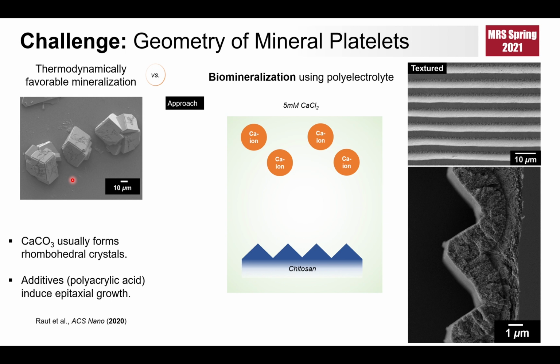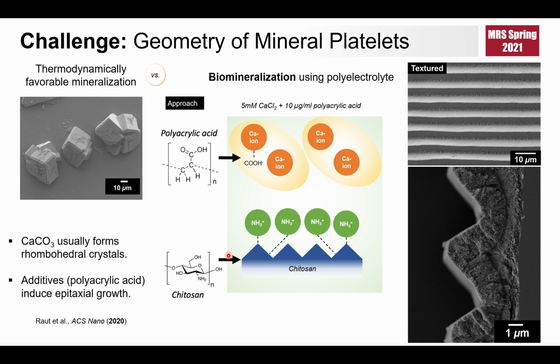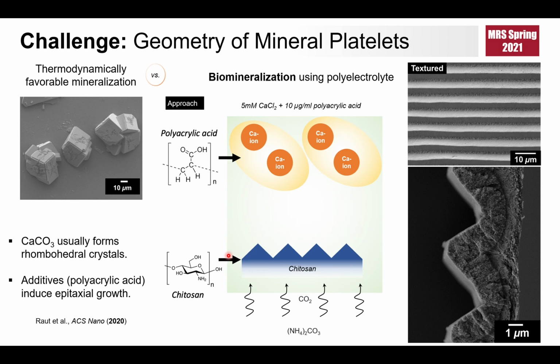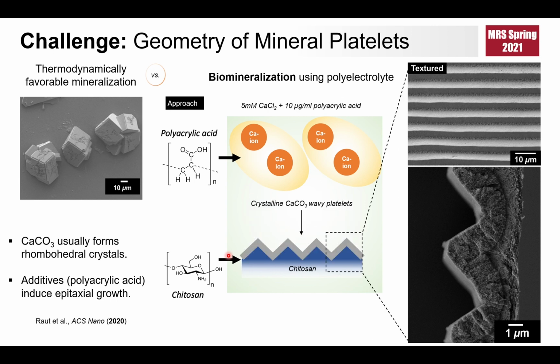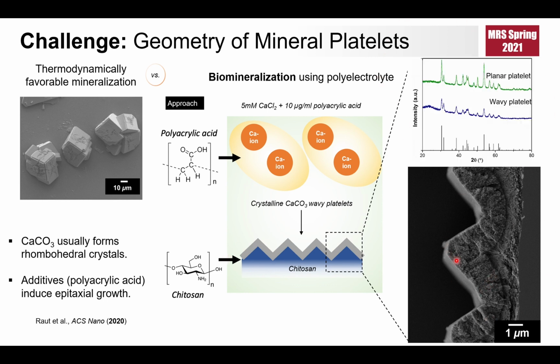We investigated such a biomineralization strategy on micro-patterned chitosan surfaces. To mimic the biomineralization process, a polyelectrolyte, polyacrylic acid or PA, was added to the mineralization precursor containing calcium chloride. Here PA, being anionic, encapsulates the positively charged calcium ions and in turn attaches to the positively charged amine-rich chitosan surfaces. This results in epitaxial aggregation of calcium ions on the chitosan surface that subsequently crystallize into the aragonite mineral. This biomineralization process results in the formation of wavy platelets that basically follow the underlying chitosan topography.